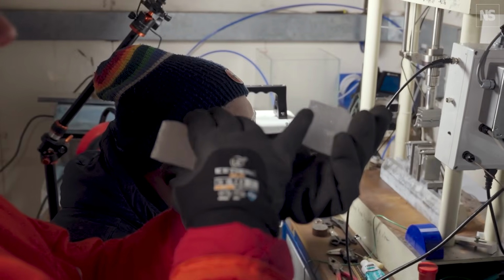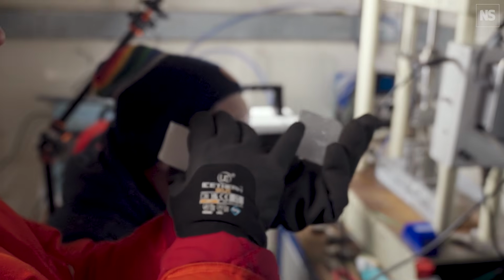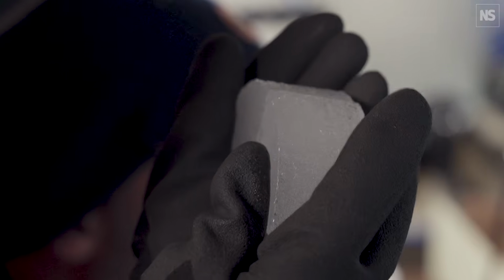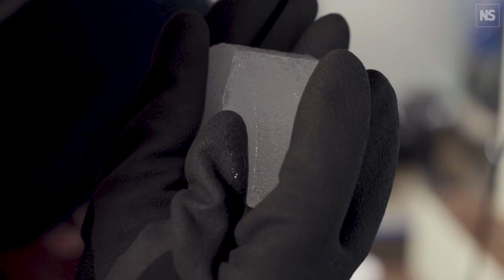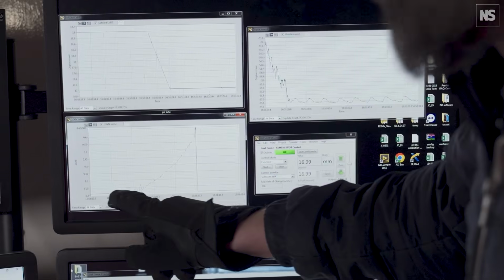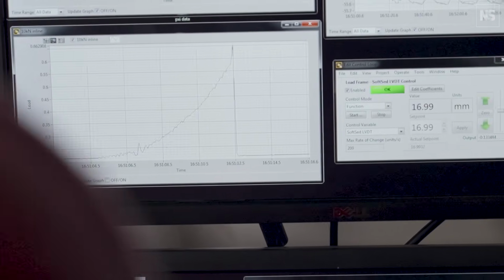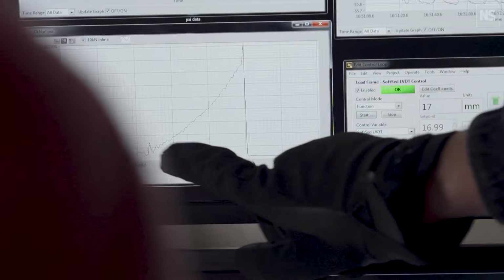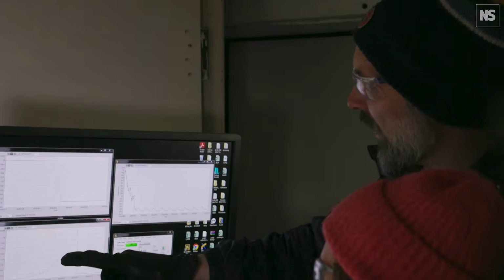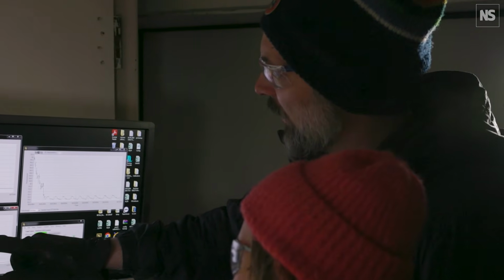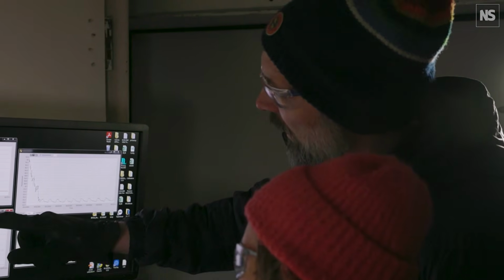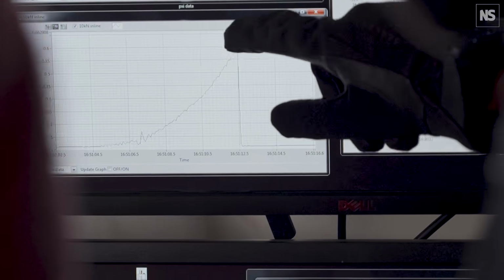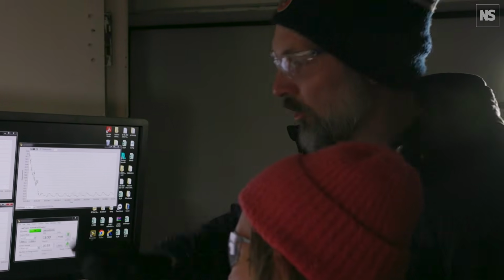So this is the fractured surface of the ice that we've just broken through. So we'll measure the length of that edge and then use that to calculate the fracture toughness. So this is the background levels where there was no load on the sample. And as the piston came down, you can see that there's a load being increased. It's non-linear because ice has cracks in it. And you see a nice linear elastic phase here, and then you can see stress build up, and then you see there's a crack and there's a stress drop.